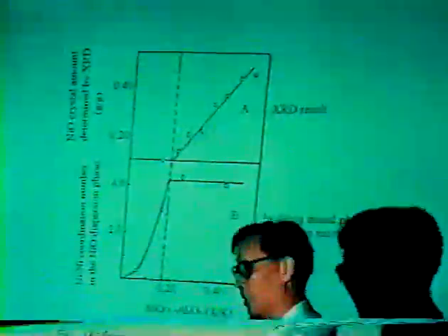There is a turning point here. The turning point is just the same as the turning point found by X-ray diffraction, the so-called threshold or critical loading. In the monolayer state, the nickel-nickel coordination number decreases sharply as the loading decreases. At low loading, the nickel-nickel coordination number is much less than 1. But throughout the monolayer state, they attain about 4 nickel-nickel coordination number.